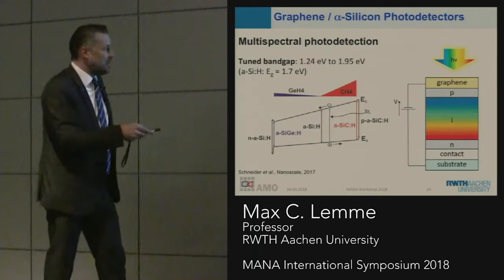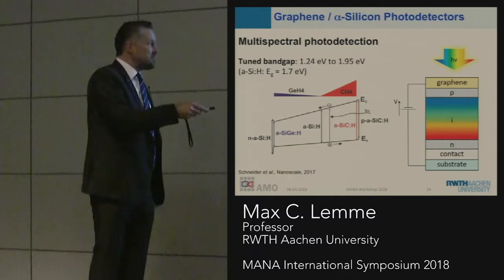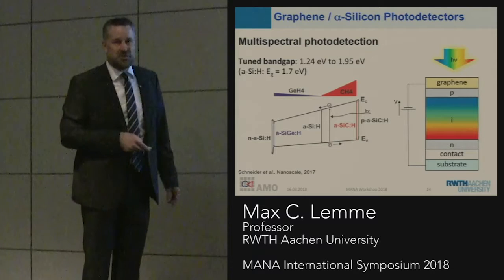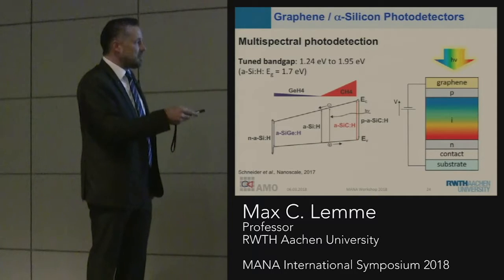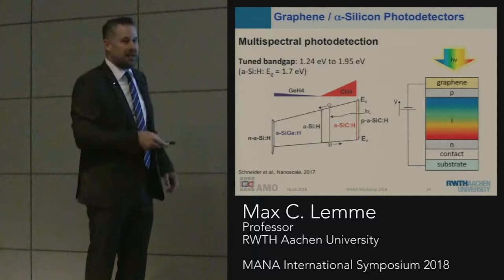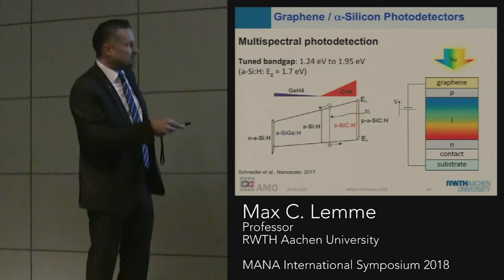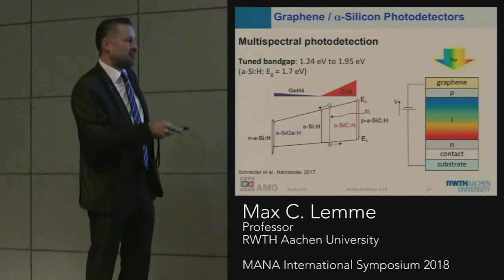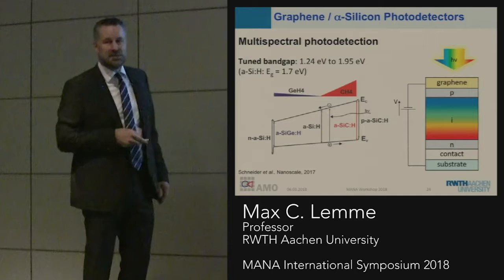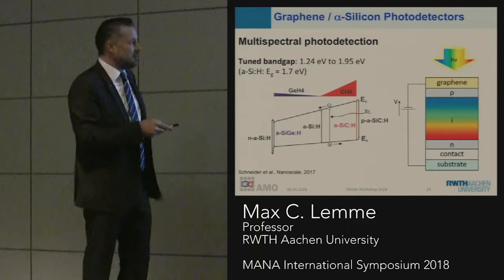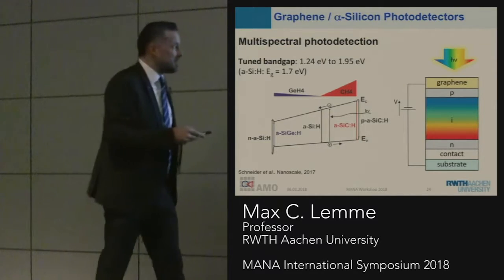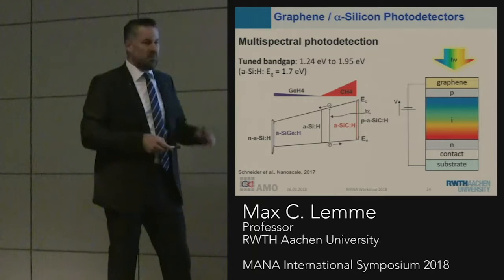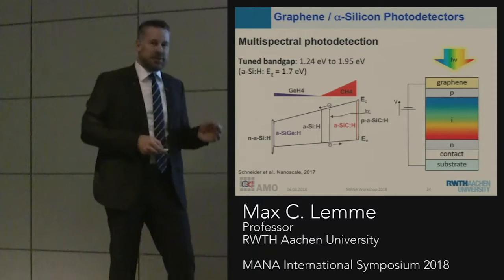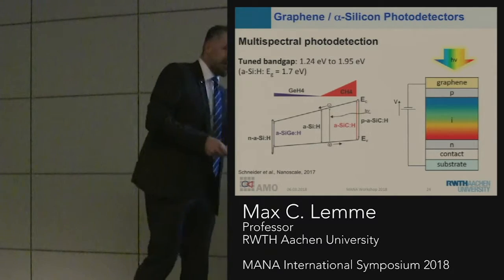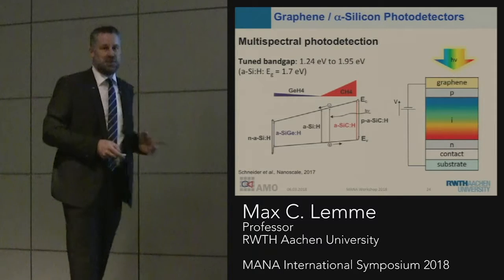And because the penetration depth of the light is different for different wavelengths, we can also bias this differently. We can extract carriers from certain regions preferentially by applying different bias voltages. So by running an algorithm, we can actually make a photodetector that is multispectral. We can detect the color with a single photodiode.